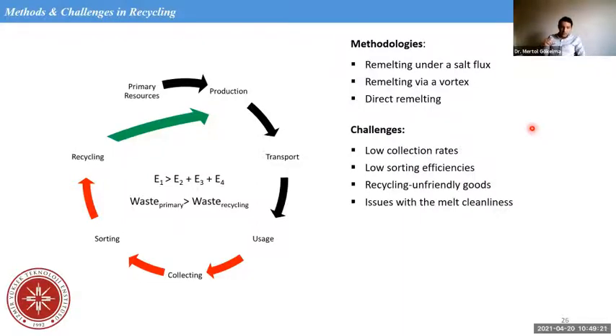And the challenge here is the low collection rates. We cannot collect enough scrap in the world. That's a big problem. Low sorting efficiencies. In metallurgy, our efficiency of remelting is over 98-99%. But if you calculate this with the collection rate, which is 10%, 20%, and sorting, which is not better than 50-60%, they lower the efficiency of recycling, not the metallurgy.